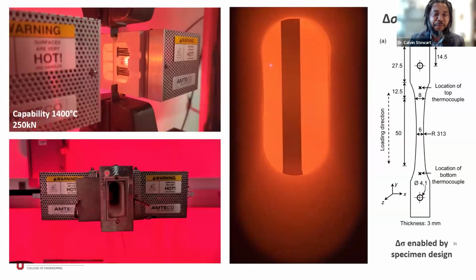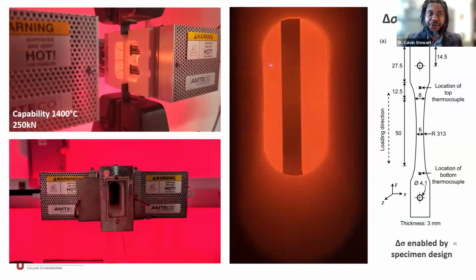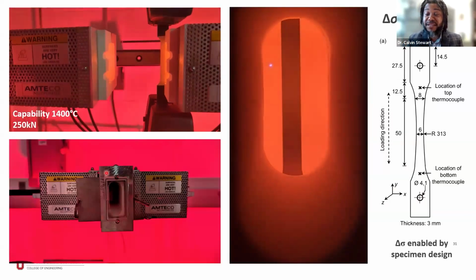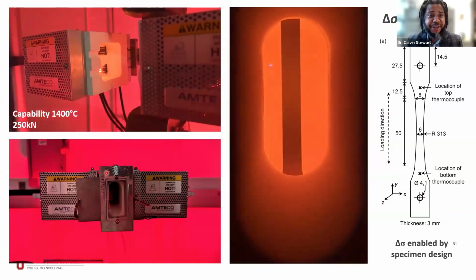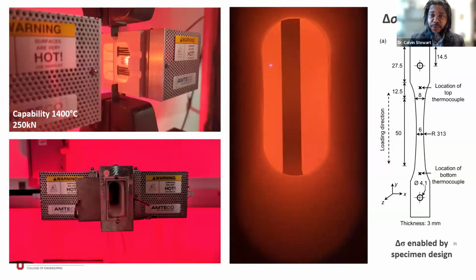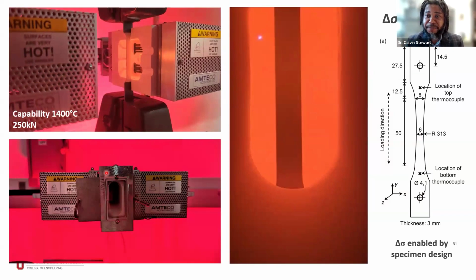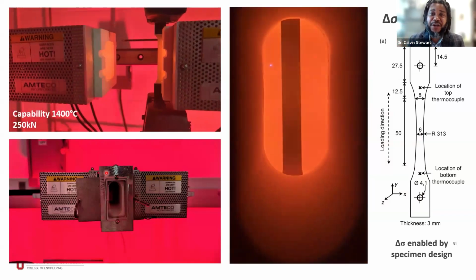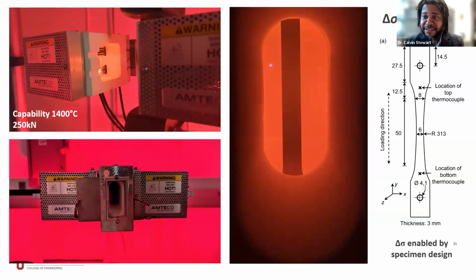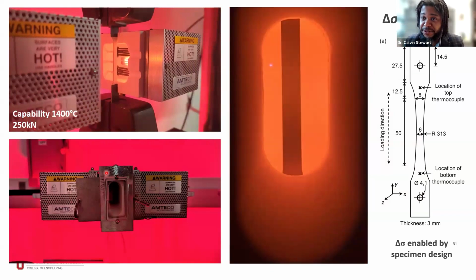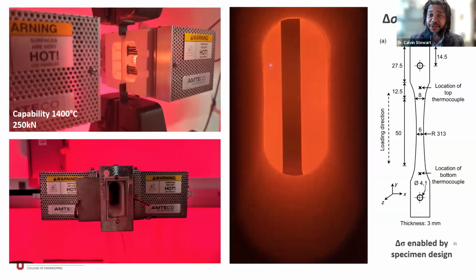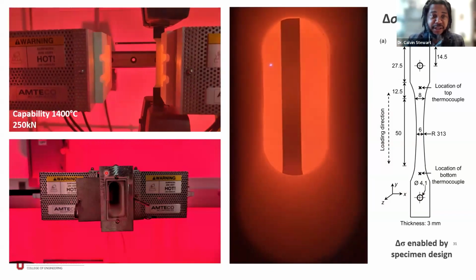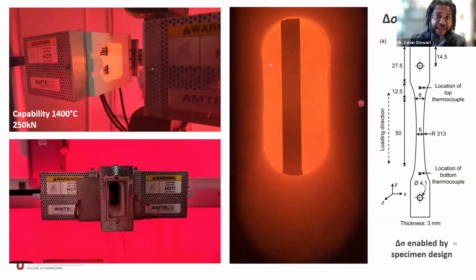We'll get to it. So in our lab in the last 2 years, we've built setups to do exactly these gradient temperature tests. Whether it's the Delta Sigma test setup, where we have 2 machines configured for this that can test up to 1,400 degrees Celsius with load capacities of 250 kilonewtons, that allows us to test these gradient samples.